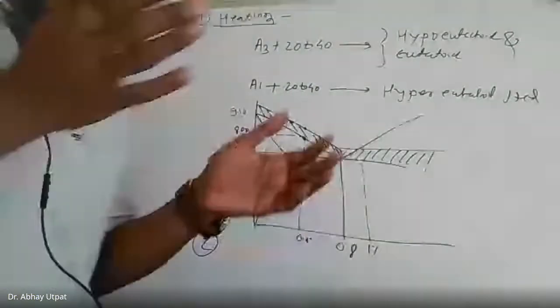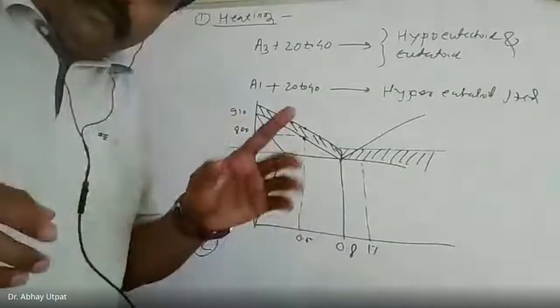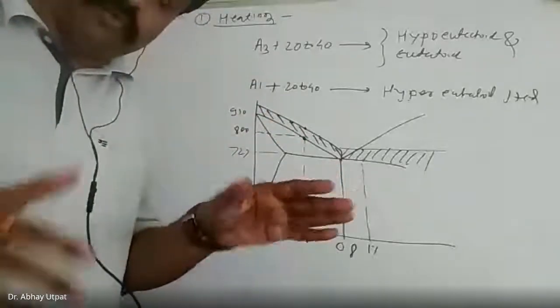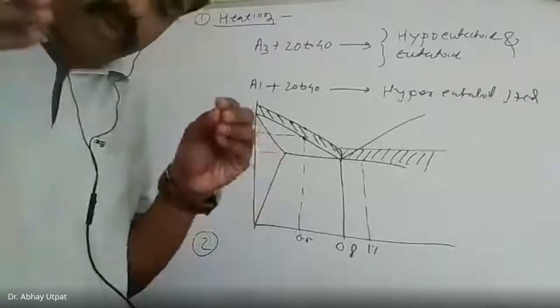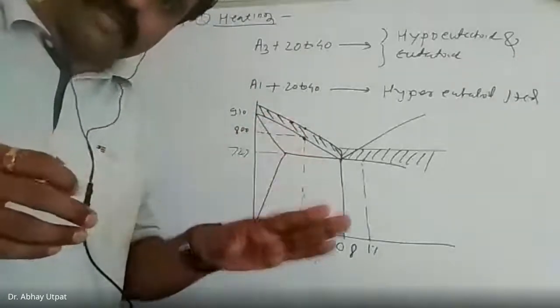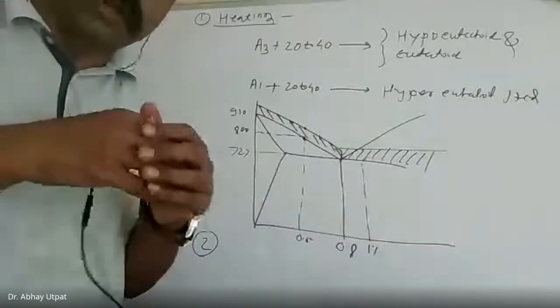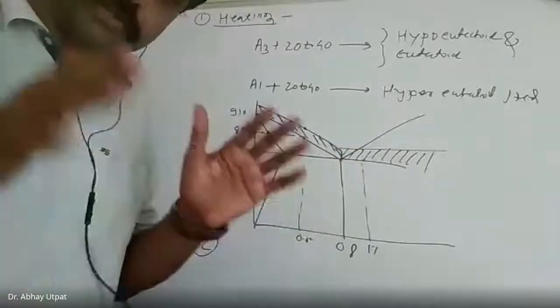Means if cross section is 25 mm or up to 25 mm, you have to wait for 1 hour to form homogeneous austenite. So if it is very small, the soaking may be less. It may be 10 minutes or 15 minutes. But usually casting sizes are bigger. That's why 1 hour is sufficient for getting the homogeneous austenite.